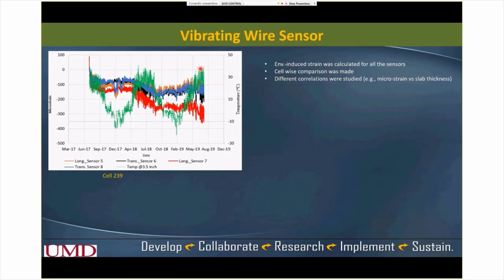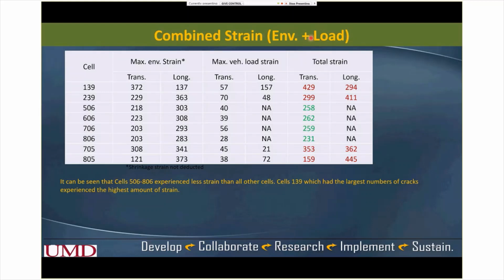We also have the strain from the wheel load. We combined the environmental induced strain and the load induced strain, and in this slide you can see we compared them. As anticipated, you can see cell 139 has more strain than all other cells, and that's probably the reason why we have seen more cracks. Now these four cells, cells 506 through 806, you can see the strain in these cells is relatively low, around 40% of their modulus of rupture. That's probably another reason why they are not cracking.